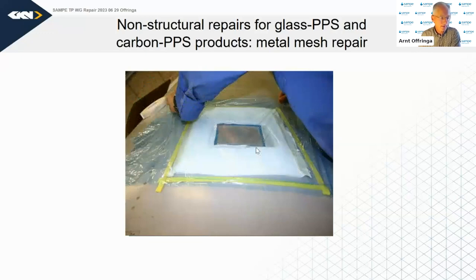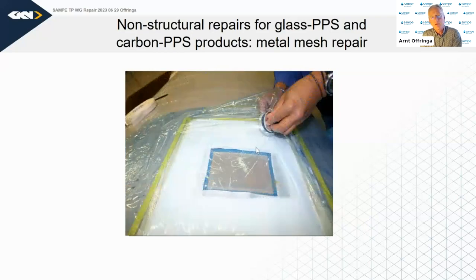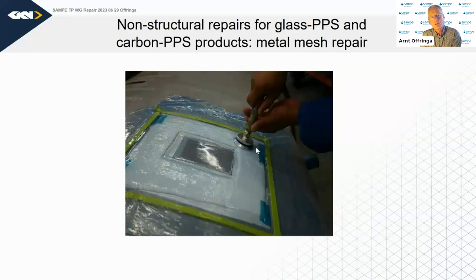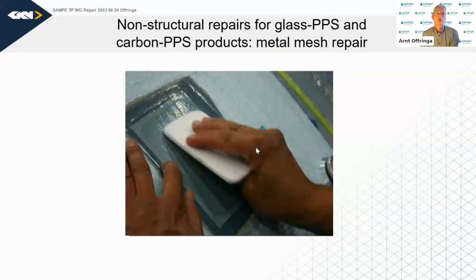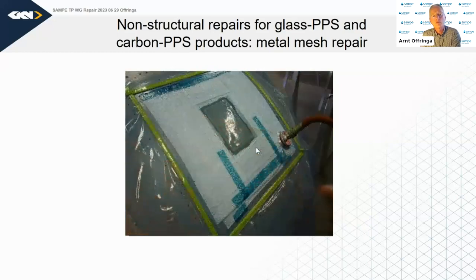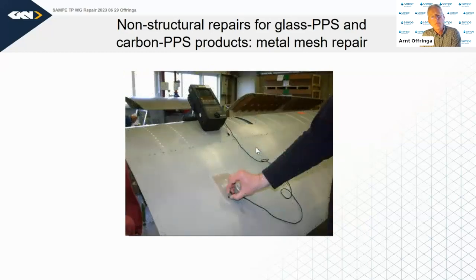And this is important, that we often need a bit of pressure or some form of maintaining form and shape of the product. So if we're thinking thermoplastic repair with welding or melting, then it becomes even more important. So here we have the vacuum application. Put vacuum on the whole thing, with a small cold plate, and cure the resin. A spatula, once again, forces out as much epoxy as possible, to keep the weight to a minimum and the thickness to a minimum. Then you cure with a heating blanket or without, and then you're done.